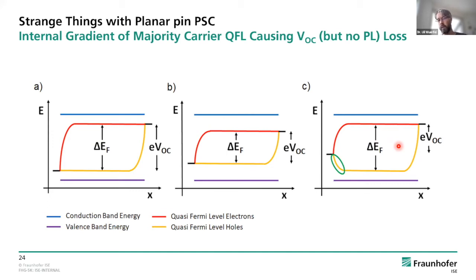There is no other possibility, because if the gradient would already start from very inside, from the other side of the absorber, then the separation of the quasi-Fermi levels could not be that large. Here only this kind of, I mean, it could also be on the other side. This we don't know, but at least on one side we have this situation where a part of the voltage is consumed due to a gradient in the majority carrier quasi-Fermi level, in this case the holes, but we still have an overall high charge carrier concentration in our absorber, therefore a high photoluminescence intensity.